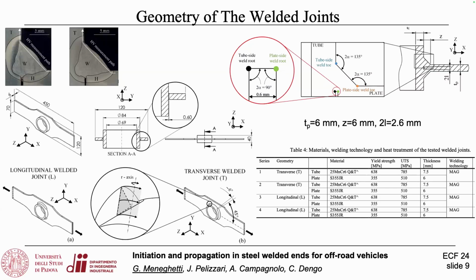You see that there is a root gap because the penetration is not complete. So you see here the reference geometry. We have the tube, we have the plate with the hole, we have a partial penetration. If you consider the sharp V-notches, we have the plate side toe, which is a potential crack initiation point, but also the weld toe at the tube side, but also the root.